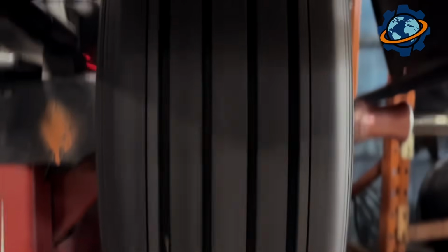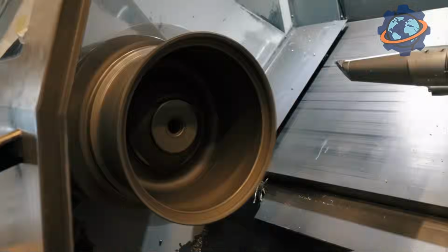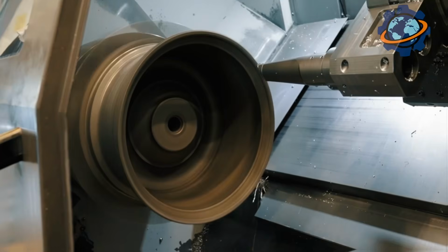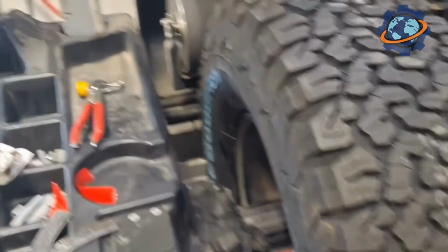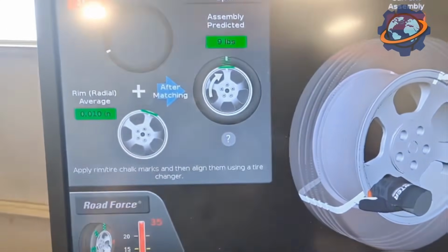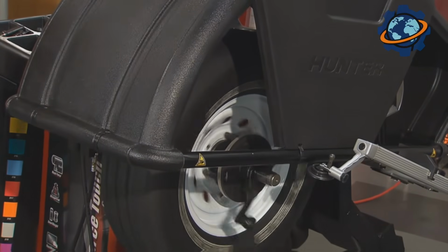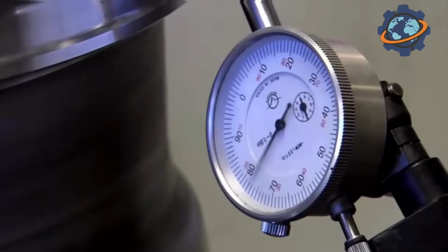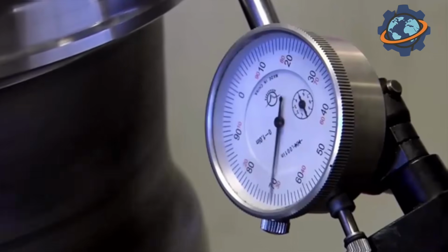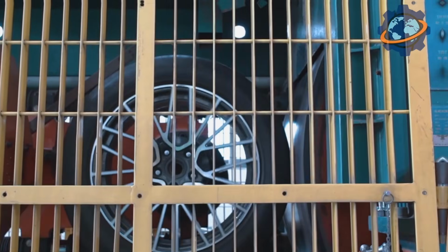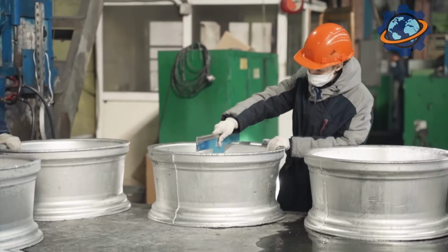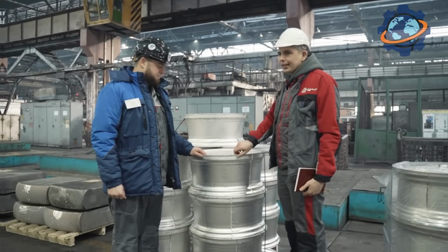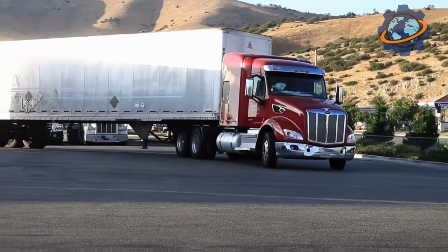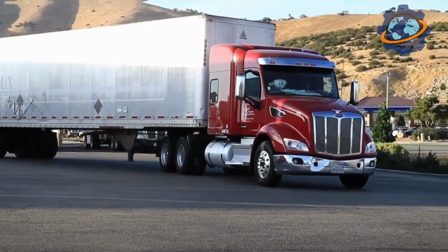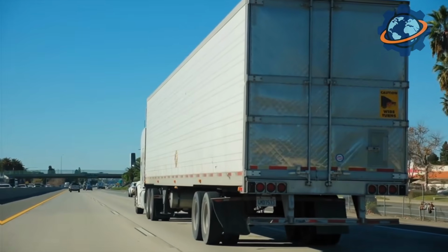Speaking of wobble, one of the most critical tests on a finished wheel is the run-out check, deviation from a perfect plane and circle. The wheel gets mounted on a specialized fixture and spun. Sensors measure how much the surface deviates from the theoretical ideal. If the wheel runs out even a few hundredths of an inch beyond spec, it goes back for rework or gets scrapped. A semi rolling at 75 miles per hour with 45,000 pounds of cargo doesn't forgive wheel runout.